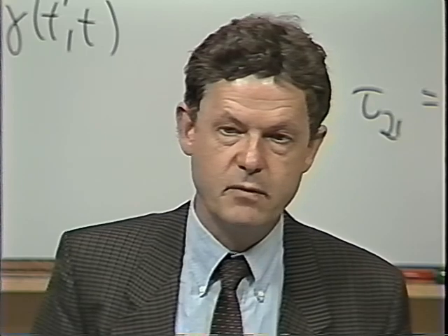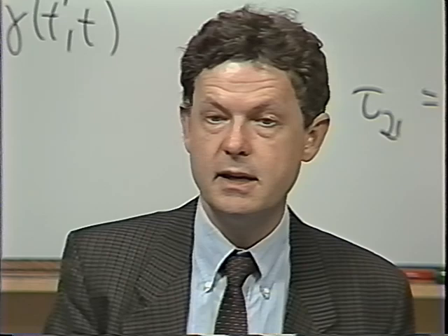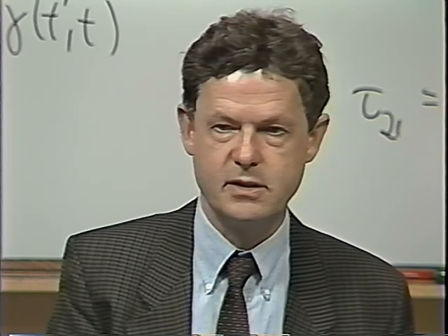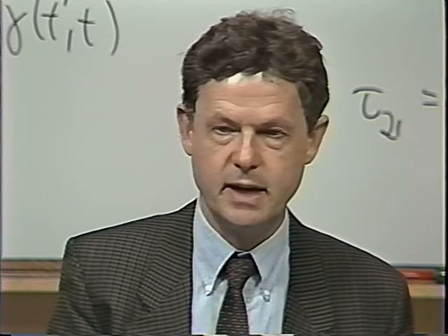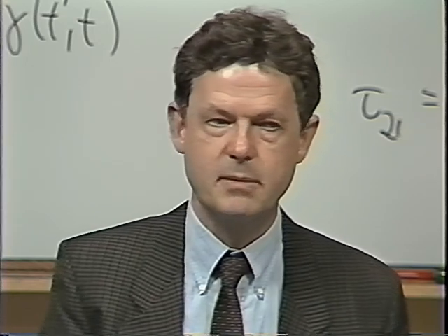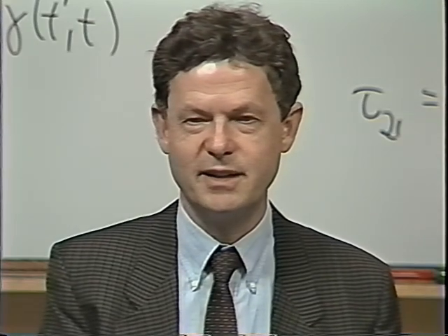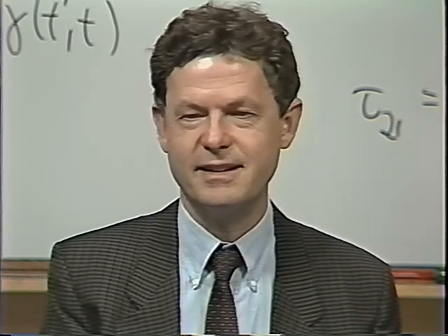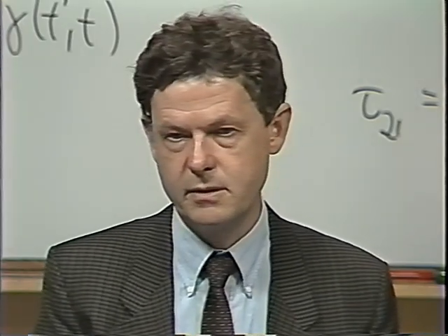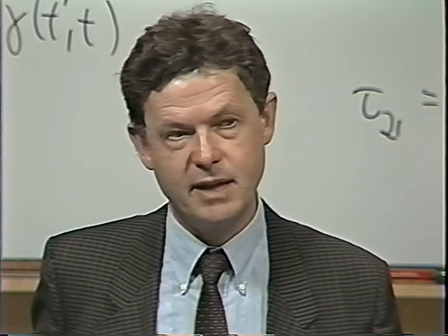Soskey tried to use the same format and extended it to model three things: shear, uniaxial extension, and equibiaxial extension, and found that it doesn't work. You really have to compromise if you want to do that. Larson did something similar in a paper with Khan, and you somehow have a hard time to formulate a simple representation of the strain function and still accommodate several flows. So if you stay within one class of flows, you're okay with that modeling.